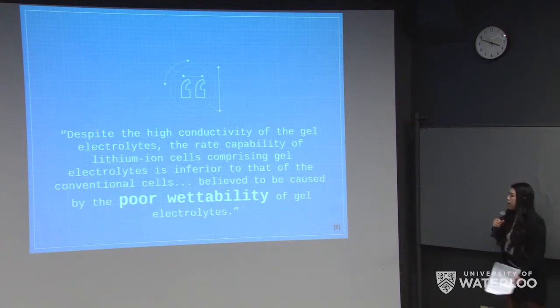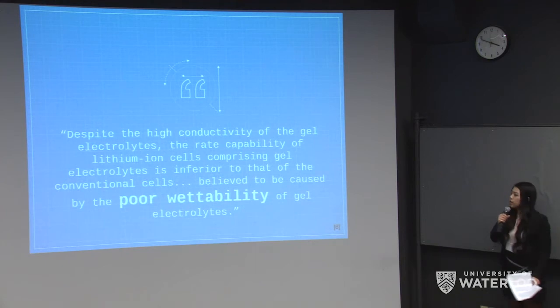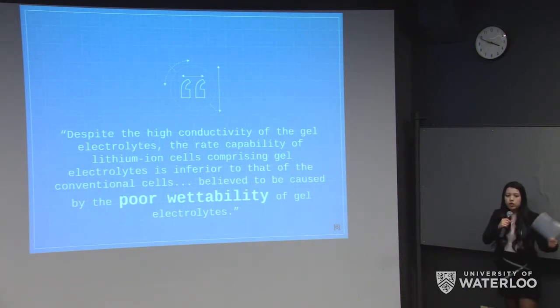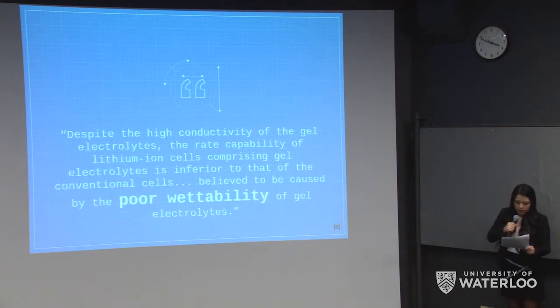So according to Chen, despite the high conductivity of the gel electrolytes, the rate capability of the lithium-ion cells comprising gel electrolytes is inferior to that of conventional cells, believed to be caused by the poor wettability of gel electrolytes. Now, this referred to the inability of the gel electrolyte to properly wet the battery separator, which in turn hindered the traveling of ions between the different electrodes. Although the electrolyte didn't leak out of the battery anymore, it caused some other problems due to the poor wettability.